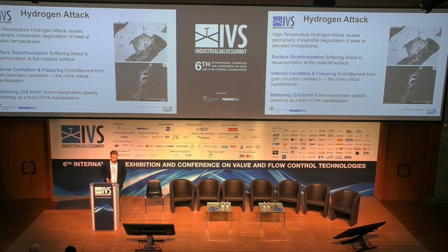So having the surface decarburization, the internal cavitation, and fissuring, and once you're getting very deeply inside this kind of mechanism, you also start noting some blistering. So the penetration inside the structure and the dilation of the lattice. So you're seeing some very nice bubbles, like you can see on the photo below.